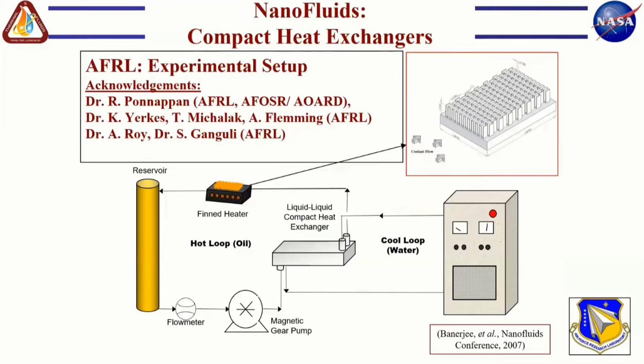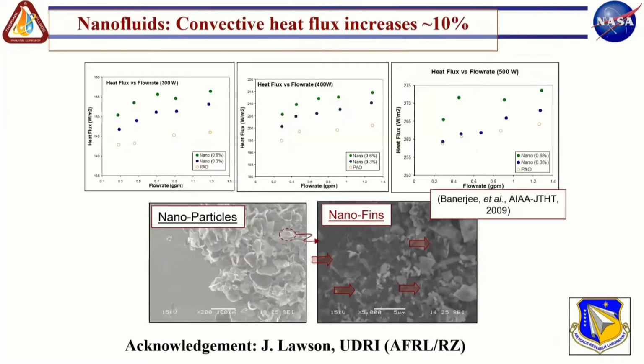So, this is a work that we did at Air Force Research Lab, where we had a flow loop where there is a hot oil loop with a fin heat exchanger on one side, and then a cold water loop on the other side. What we decided to do was, the hot oil loop contained polyalpha olefin, and we put nanoparticles in the flow. And we looked at the characteristics of the material properties as well as the type of thermal response that you get. And so here is some raw data.